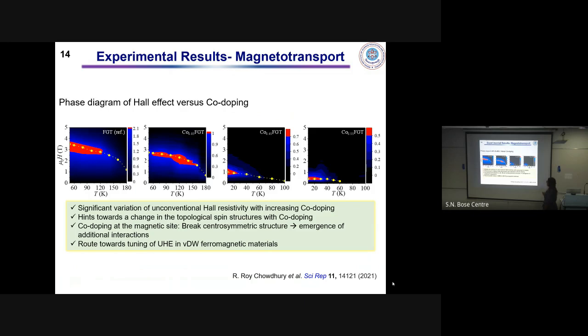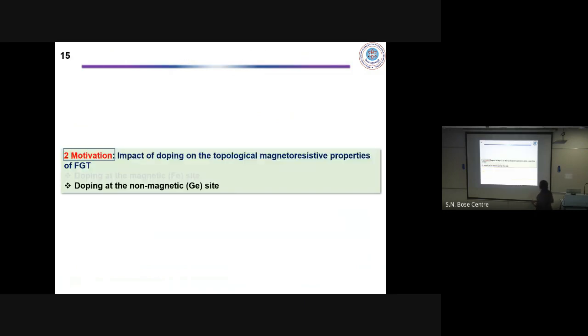So basically, this shows a change in the spin textures with cobalt doping, and this might be because of the emergence of some additional interaction that we don't know because we didn't have any probe to investigate that. So we believe that this provides a route towards tuning of the unconventional Hall effect in van der Waals ferromagnetic materials. Now I'll move on to the second part. It was known